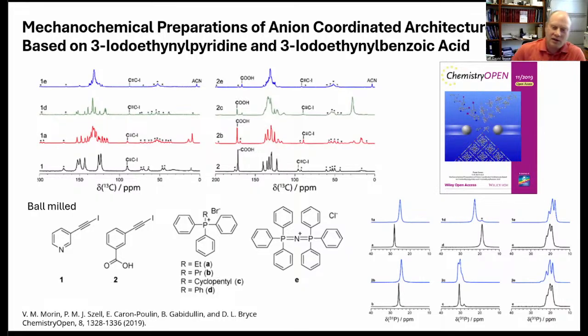So here's an example of one of our mechanochemistry studies analyzed by solid state NMR. What I'm showing you here, the bottom left, are some of the compounds that we're looking at. So compounds 1 and 2 are halogen bond donors. These are iodoethynyl substituents on some aromatic rings. And the iodine at the end of this triple bond can form that sigma hole, as I mentioned, and act as an electron acceptor, in this case, forming halogen bonds with either the chloride or bromide anions shown in the molecules or the salts on the right.